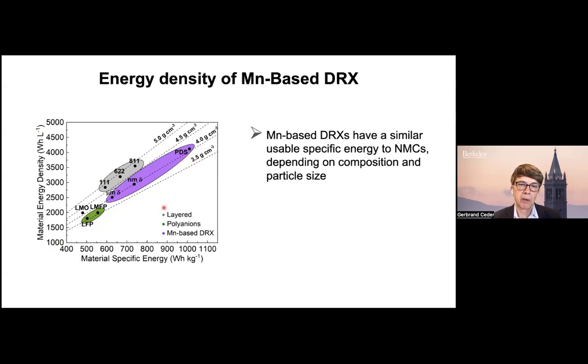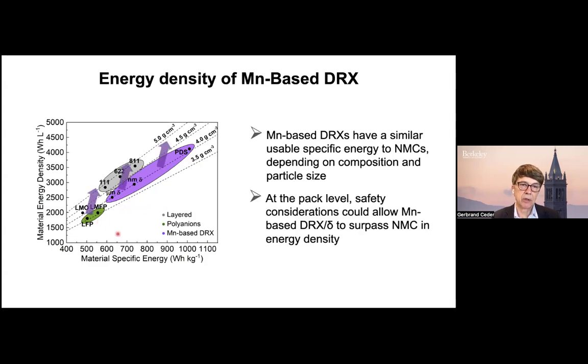But to go back to the lessons we learned at the beginning with LFP: because Delta DRX only uses manganese as the redox couple, and at the top of charge only uses manganese 4, there's no oxygen redox. You would expect excellent thermal stability from these materials. At the pack level, we know that if you get thermal stability, you get major benefits. These materials would be quite competitive with NMC materials in specific energy and energy density, though potentially a much cheaper and much more earth-abundant version.